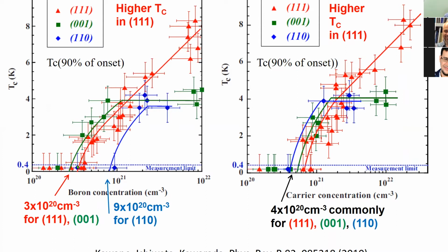So the starting superconductive transitions were almost the same or a bit low, 3 times 10 to the 20s per cubic centimeter. But the TC goes up according to the boron concentrations, and the 001 case stopped, but 111 just goes high and high. Right now, one of the highest we can reproduce is almost 10 kelvins.